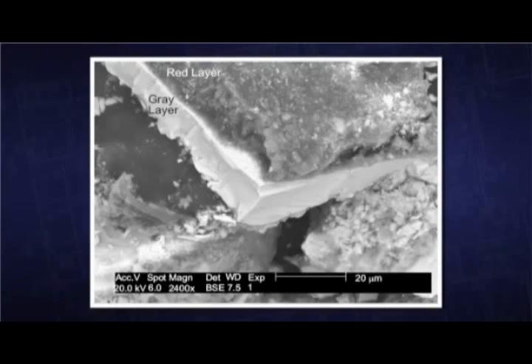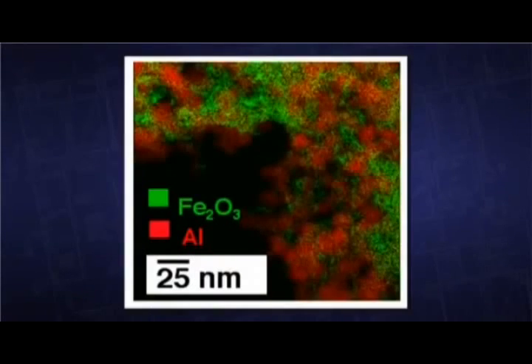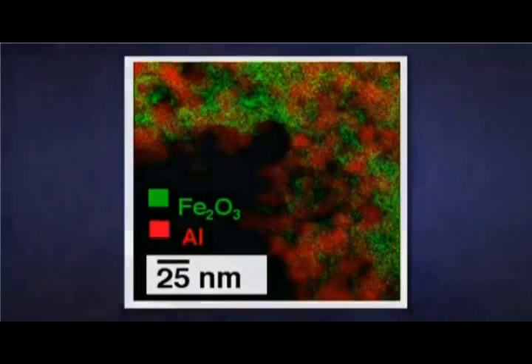What we have found is a modern version of thermite, which we call nano-thermite, which is produced in a different way. It is not just two powders being mixed. The material is actually built from the atom scale up. We call it the bottom-up procedure, which is what you do in nanotechnology. This has two consequences for the nano-thermite, which distinguishes it from the classical thermite. First, the ingredients are much smaller, which means they react faster and are more easily ignited.